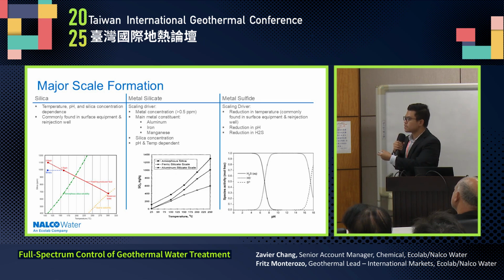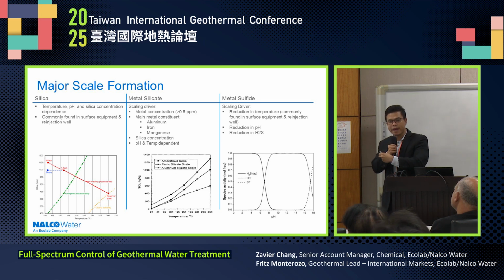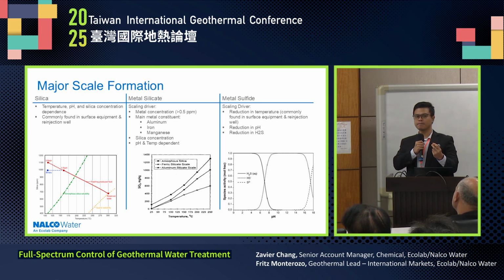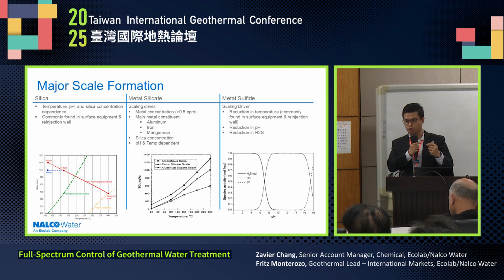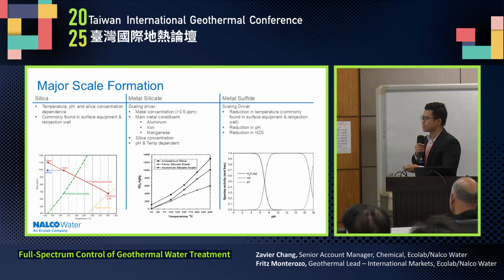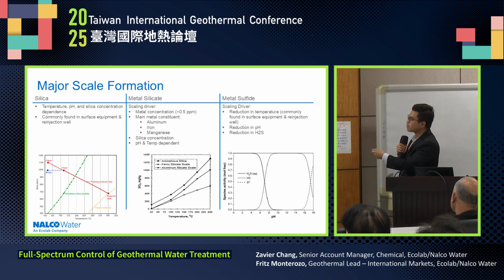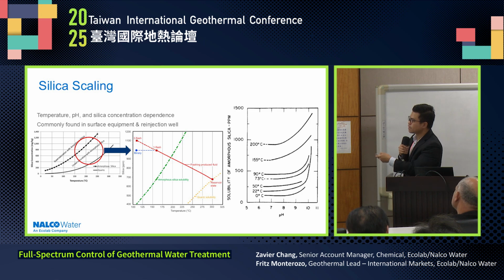Metal silicates, iron silicate, show the same behavior as amorphous silica, but magnesium silicate is different. It is less soluble in high temperature environments. That's why in systems where you have intrusion of cold water, you can see smectite, which was mentioned in the presentation earlier. So this one is also pH and temperature dependent. And metal sulfides, if your system has high H2S, there is high tendency of metal sulfide formation.